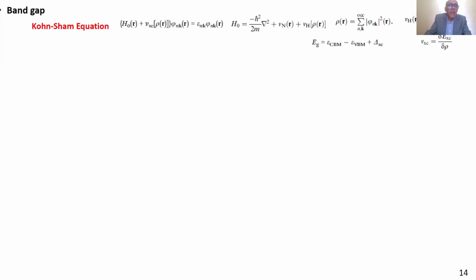But I give some example of the method used for some property looked for. For example, for band gap, if we want to determine the band gap of our materials, we can, of course, use the Kohn-Sham equation, and many approximations are available: LDA, GGA, modified BJ, hybrid, which introduce a part of exact exchange into the Hartree term, which is a mean field term, and also other approximations, and that helps to determine the gap, which depends on the approximation used.